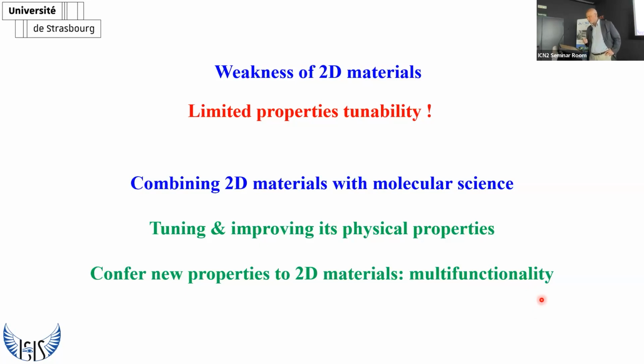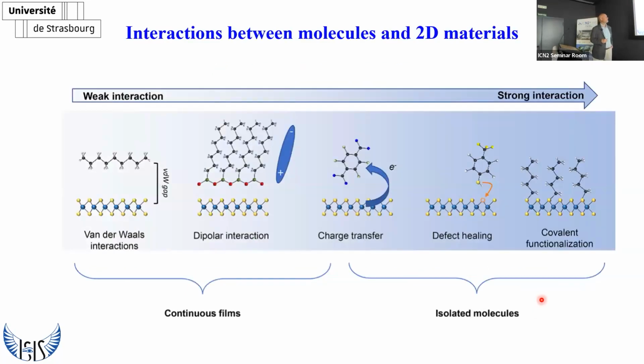Now, the interaction between molecules and 2D materials can be quite diverse, from the weakest, which are the van der Waals interactions, to the strongest, which are the covalent functionalization. And in between, you have a number of other types of interaction with different magnitude, that can be dipolar interaction, charge transfer, or defect healing. The part on the left are those that are targeted at creating continuous films of molecules on the 2D materials, whereas the one on the right is more targeted at anchoring isolated molecules.